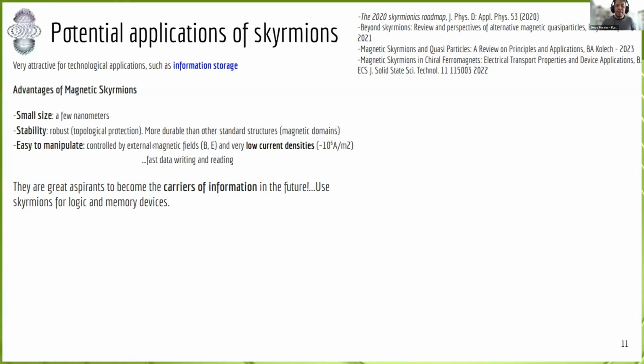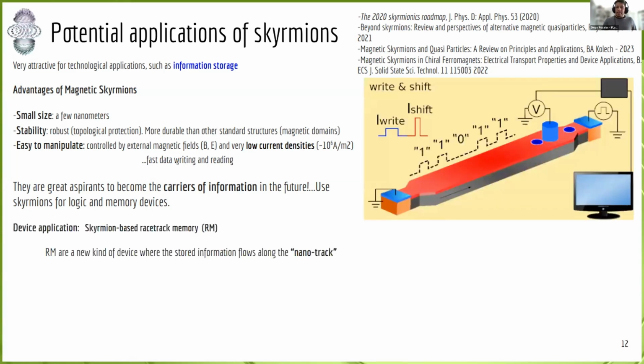People can control the magnetic skyrmion using electric field or magnetic field and very low current density. People are trying to use this skyrmion in this kind of device. This is an animation I made of what is called the racetrack memory. The idea is to create a skyrmion on one side of this track by the injection of a spin polarized current, and then move the skyrmion or the skyrmion pattern using another spin polarized current, and then detect the configuration in another part or edge of this track.